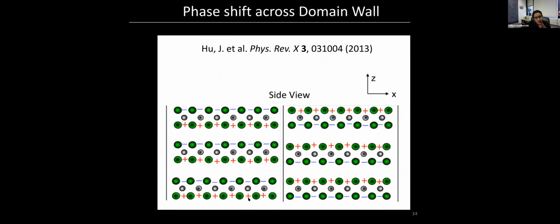So as it turns out, this FeSeTe is really intriguing because Jiangping Hu wrote a paper in 2013 where he showed that if you consider all the important interactions, nearest neighbor, next nearest neighbor, and so on, then what you find is a very interesting kind of superconductor where, so this is one of the layers. This could be Fe arsenic arsenic, or iron selenium selenium. But in any case, what you find is that the sign of the order parameter switches from the top to the bottom layer. So there's a pi phase shift in the sign of the order parameter between the top and the bottom selenium or arsenic layers.